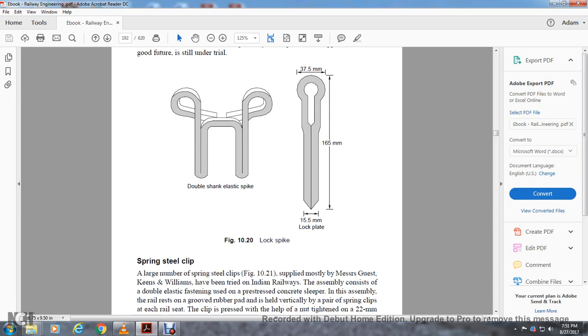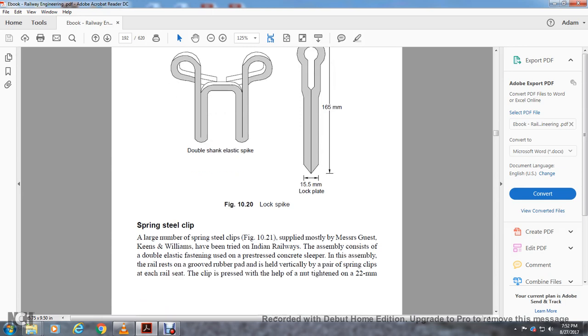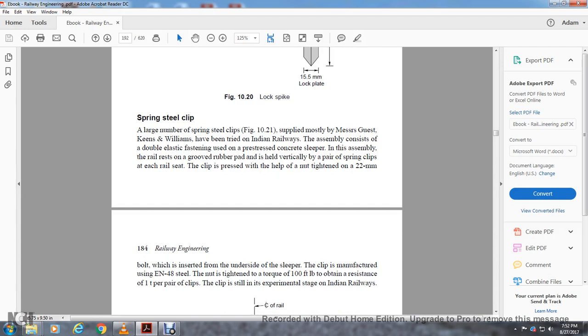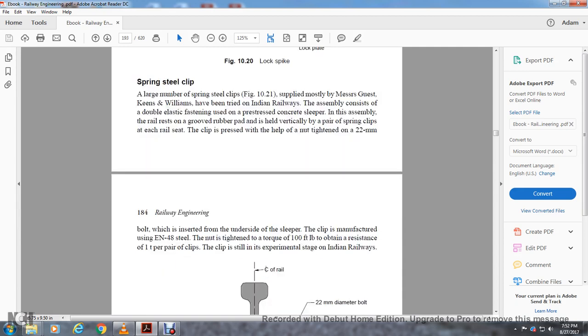Or spring steel clip. A large number of spring steel clips, figure 10.21, supplied by Messrs. Guest and Keen Williams, have been tried on the Indian Railways. The assembly consists of a double elastic fastening on pre-stressed concrete sleepers. The rail rests on a grooved rubber pad, and is held vertically by a pair of spring clips on each rail seat. The clip is pressed with the help of the nut and tightened on a 22-mm bolt. A bolt with an inserted from the underside of the sleeper. The clip is manufactured using EN48 steel. The nut is tightened to a torque of 100 foot-pounds to obtain a resistance of 1 ton per pair of clips. The clip is still in the experimental stage on the Indian Railways.